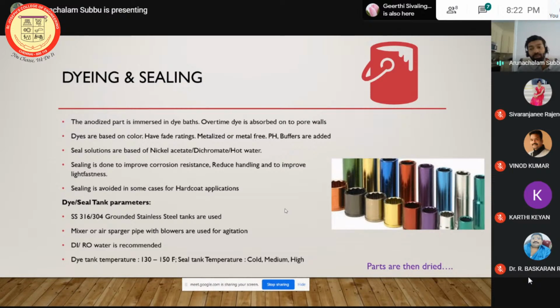And the next step is the sealing process. After the dyeing, it goes into the seal tanks, where you have a nickel acetate chemistry or dichromate chemistry, which blocks the pores completely so that the dye doesn't come out soon. The sealing is also done to improve the physical properties of the coating. It improves the corrosion resistance, improves the light fastness, and reduces the effects of handling and all those things.